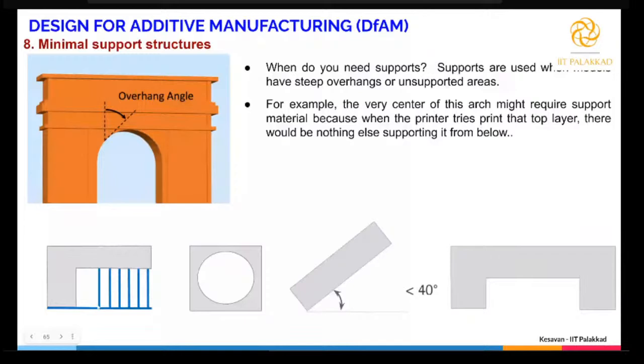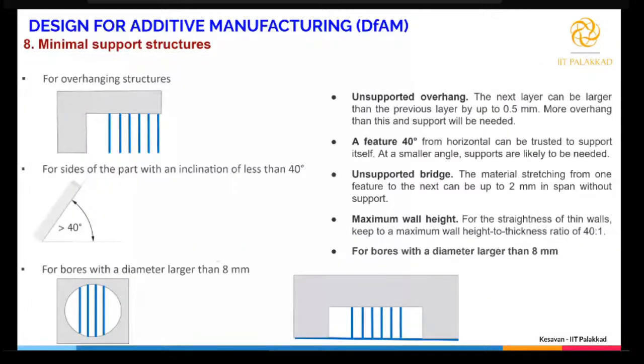But there are some conditions based on which you need to give the support. For example, if the diameter is more than 8 mm, you need to give support. If the inclination is less than 40 degrees, you need to give support. If the overhang is considerably larger, you need to give support. You cannot print the component without the support structure. That's the reason that during design itself, you need to think of avoiding such overhanging dimensions. For example, if the hole size is greater than 8 mm, you will end up with this kind of issue. Try to avoid these dimensions or overhangs. You need to have all these things in your mind before you design your concept for printing by using additive manufacturing. Like what you're seeing here, this is a very efficiently printed component using support structure.